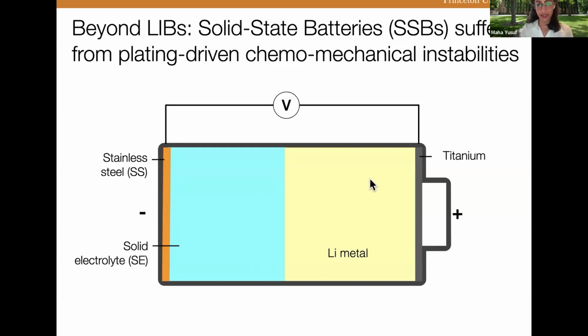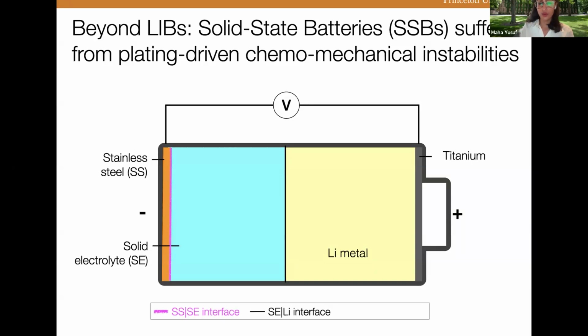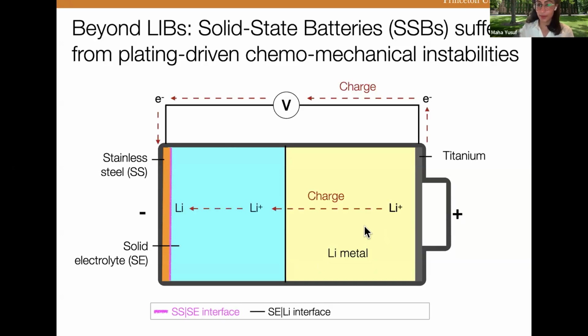So you can see in this schematic, we have lithium metal, solid state electrolyte, hence the solid state battery, and this current collector. Now what happens during charging is that we move lithium ions from the lithium metal through the electrolyte and then plate at this interface of stainless steel metal and solid state electrolyte.